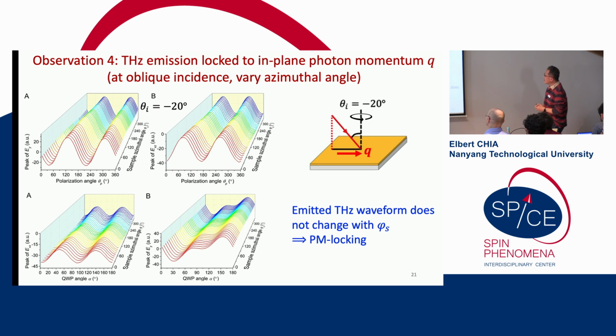And so the next thing that we did was we rotated the azimuthal angle. So we fixed the incident angle at minus 20 degrees. So we fixed the direction of Q, and we just rotated the sample this way. And as you can see, as we change the sample azimuthal angle, there's hardly any change in the emitted Terahertz waveform. So once again, it shows that the emitted Terahertz waveform is locked to Q, not locked to the azimuthal angle.